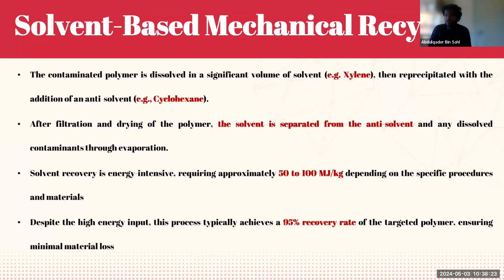So let's talk about the steps briefly. The first step involves dissolving the polymer. Then the second step involves reprecipitation. After dissolving, an anti-solvent, for example cyclohexane, will be added. This causes the polymer to precipitate out of the solution, separating it from the contaminants and from the solvent mixture. Then we have separation and drying, where it goes through filtration and drying. It's important to note that solvent recovery is energy intensive, requiring approximately 50 to 100 megajoules per kg, depending on the specific procedures and materials. Despite the energy input, this achieves a 95% recovery rate of the targeted polymer, ensuring minimal loss.